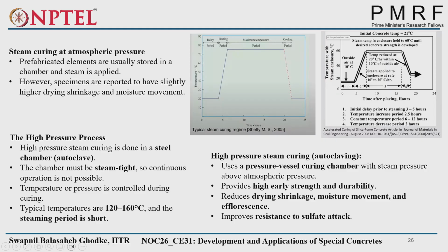Similarly, Professor Mishra has used this at IIT Kanpur. The outside air temperature is 10 degrees Celsius. For the initial delay prior to steaming, they give 3 to 5 hours after casting. Then they increase the steam applied to the enclosure at a rate of 10 to 20 degrees Celsius per hour. This is achieved in 2.5 hours, and then it is maintained constant at 60 degrees Celsius until the desired concrete strength is developed. In their case, it developed in between 6 to 12 hours. And again, the temperature decreases gradually over a period of 2 hours at 20 degrees Celsius per hour, down to the 10 degrees Celsius outside air.